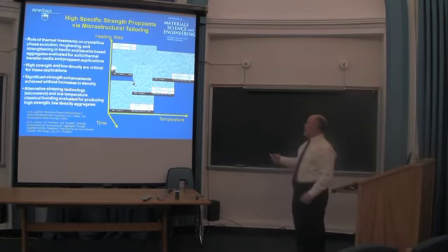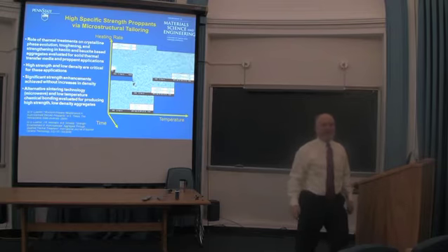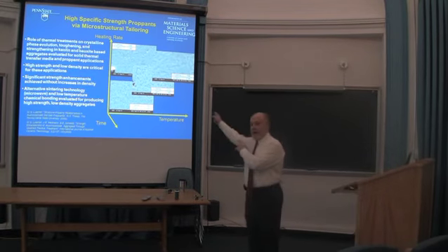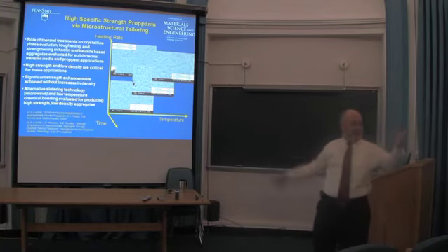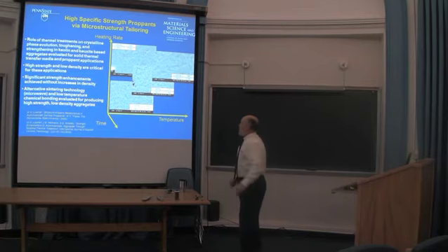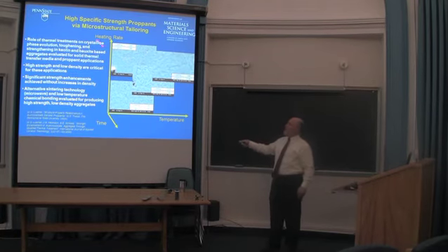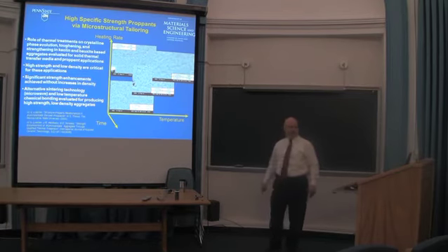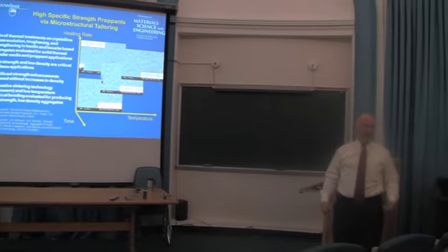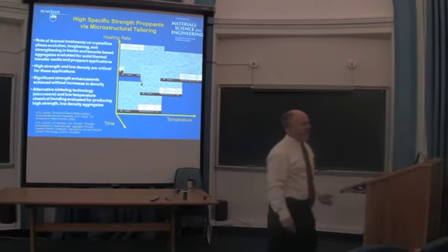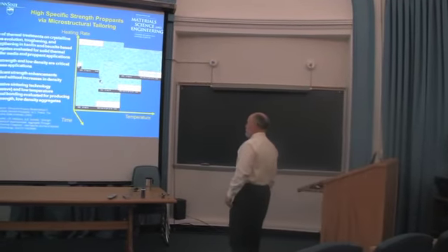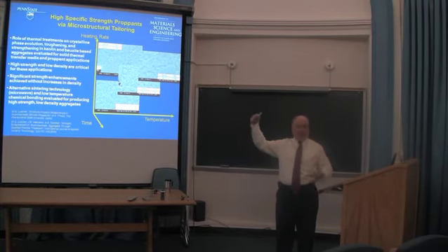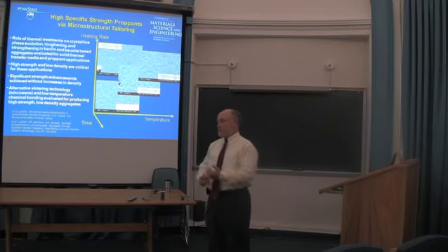We found that we could get microstructural evolution. These are large grains of, in this case, mullite forming, and the other phase there is glass, an aluminosilicate glass, very common. That's a classic ceramic earthenware, right, Steve? Okay? And what we found was that we could have a sweet spot where very rapid heating rates at markedly lower temperatures for relatively short times gave us a better or comparable product to the stuff they were cooking the bejesus out of. And the reason for it was we played with the kinetics of the cristobalite evolution. Okay? Or consumption, as it turned out. Well, that allowed this company to make more product faster at a lower temperature. Use less fuel, less time.